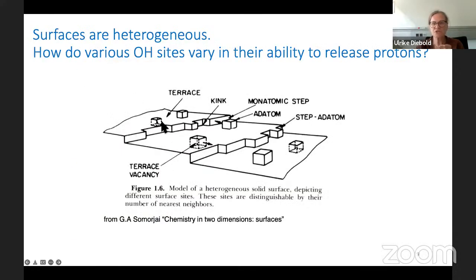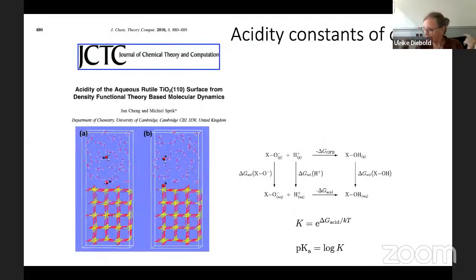Even if you have something that is not so terraced and so defective yet, if you just think of a perfect single crystal, like the STM image I showed you before, even there you have different oxygen atoms on the surface. So these were the bridging oxygens I showed you before in the STM image, and here would be a water molecule, and then depending on how easy it is for the water molecule to give off one or two protons, it depends very much which oxygen atoms you look at here, right? And so these are really nice works. There's lots of things going on with molecular dynamics simulation. So this is an older work by Michiel Sprik. And there's again this thermodynamic cycle where people try to really calculate this pKa of, let's say, TiO2 in water.